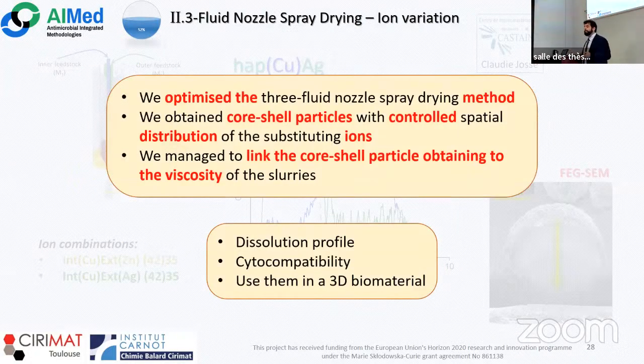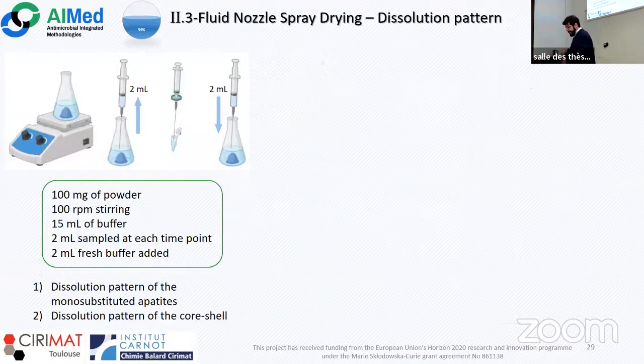In conclusion, we were able to optimize the triple nozzle spray drying technique. We obtained this kind of core shell particles, and we managed to link the concentration to the viscosity in order to even try to expand the borders of the technique. Now, what we want to do with them is see their dissolution patterns, study their cytocompatibility, and use them. At first, we studied the dissolution patterns.